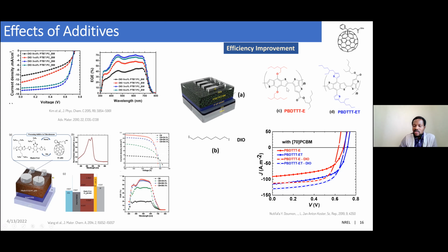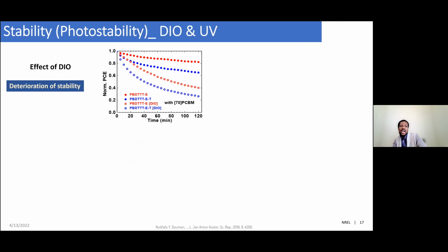And when you add it, truly the device is improved. So if you move from the red polymer, which are the closed circle curves, when you add DIO, which are the open circle curves, you can see that we have been able to improve the device current density and therefore the device efficiency. However, if you look at the stability, it seems DIO exacerbates everything. The degradation becomes more pronounced. And why is it so? What is so peculiar about DIO? So we try to understand that. We also look at another additive, chloronaphthalene.